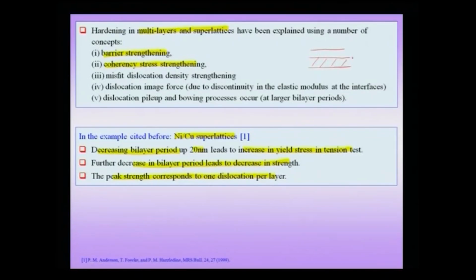So it is expected that this interface between layer A and layer B could be a coherent interface. That means there is an epitaxial relationship between these A and B layers, which gives rise to certain coherency stresses, and these coherency stresses are going to modify your local stress state, which is coming from an externally applied shear stress or a tensile stress.